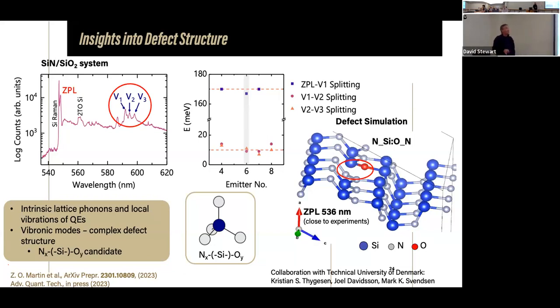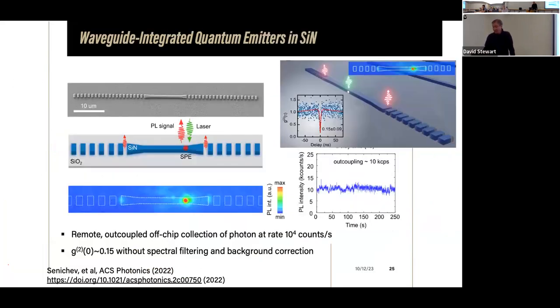And also the zero phonon line predicted by simulations is around 536, which is relatively close to what we obtained. What we obtained is around 540, 550, depending on the particular emitter. Of course, it's very important to identify the precise nature of this emitter. As soon as we are sure about this, we would probably be in a better position to optimize the emission from these emitters.